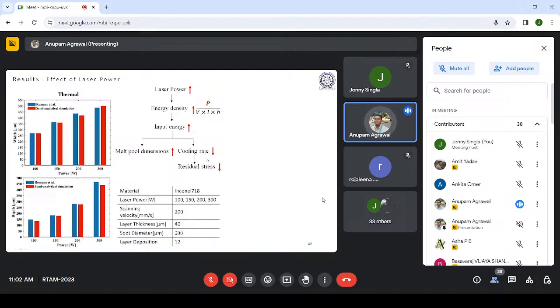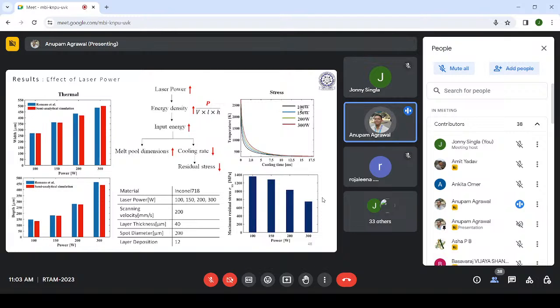What we have observed using our results was also observed by a few other researchers who have conducted either numerical simulation or experimentation: as we increase the laser power, the width and depth of the melt pool keep on increasing. That means if we want a smaller melt pool, we should go with lower laser power values. However, lower laser power might lead to higher residual stresses. So for the residual stresses for different laser powers, the residual stresses are highest with the 100-watt laser compared to 300-watt, keeping all other parameters the same. So not only one parameter can be changed.